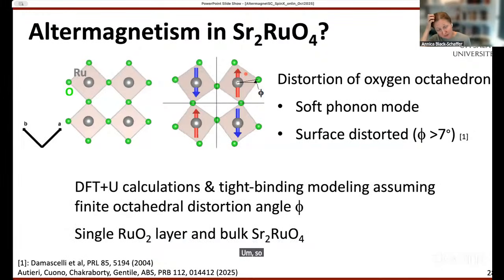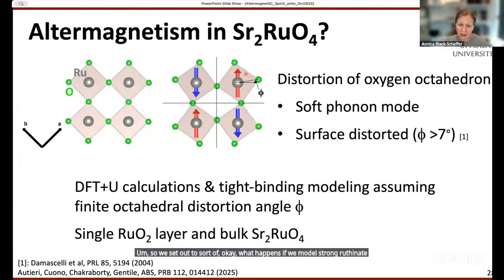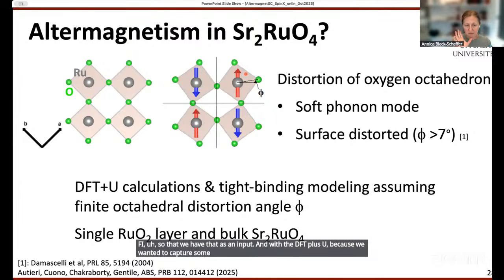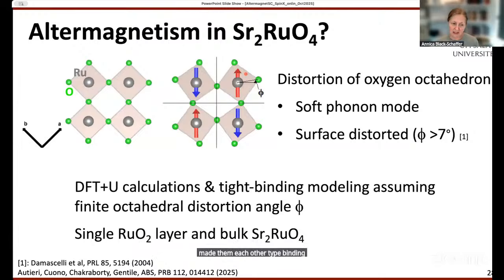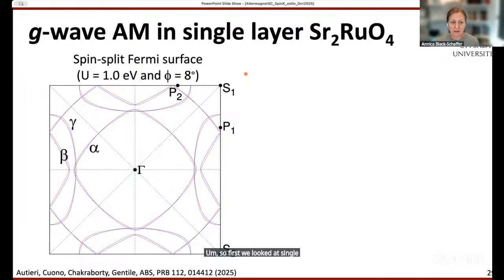So we set out to see what happens if we model distorted ruthenate and force a distortion angle, phi, so that we have that as an input. And we did DFT plus U because we wanted to capture some correlations. We took the DFT results and also made them into a tight-binding model to try to understand what's happening. So first we looked at a single ruthenium oxide layer because it's simpler. And here is then the Fermi surface.